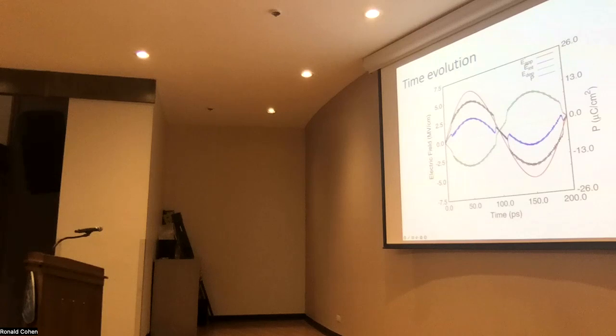So the region of interest is right here. As you can see, as we approach that switching regime, the polarization drops suddenly, and that causes equally sudden drop in the depolarizing field. And this is how we get that enhancement in the internal field. So that region where the polarization drop actually causes enhancement of the internal field, that is our negative capacitance region. And as you can see, it is very short-lived.